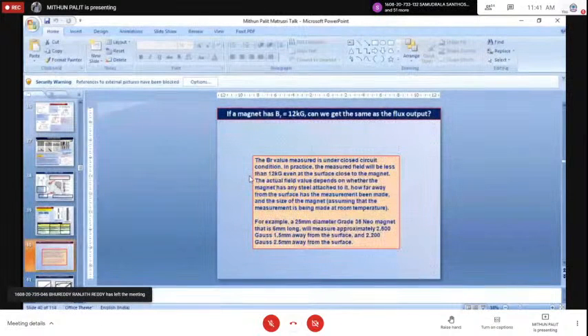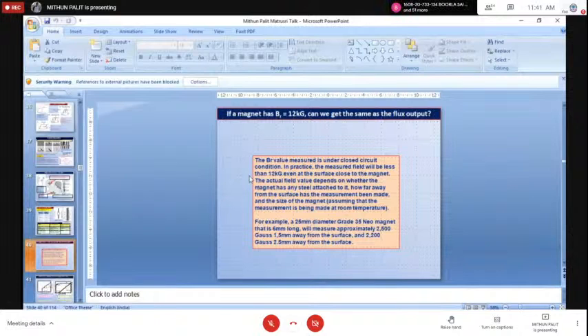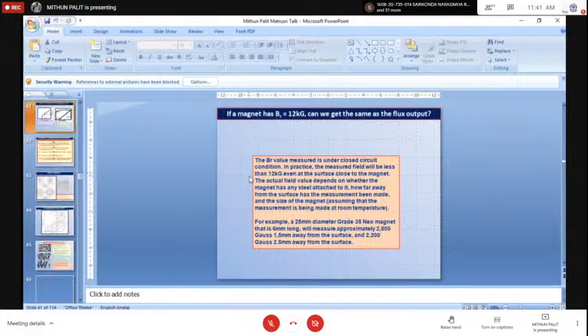Now there are three things which are important over here. One is the shape of the magnet. If I have a very thin disk, I will be losing this magnetic field quite fast away from the surface. Because of the thin shape, there will be a self-demagnetization of the magnet. And if I take a long bar, there will be very minimal self-demagnetization. There I can have more field close to the surface.